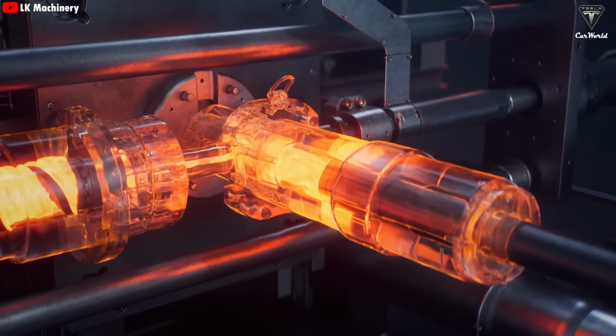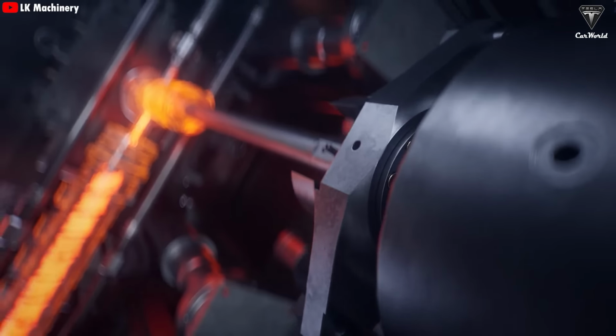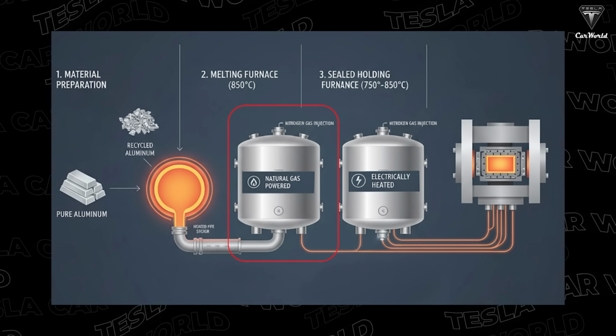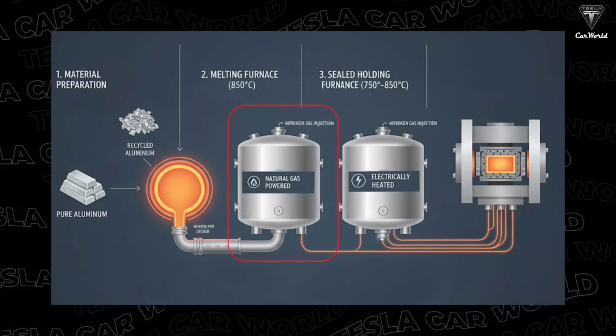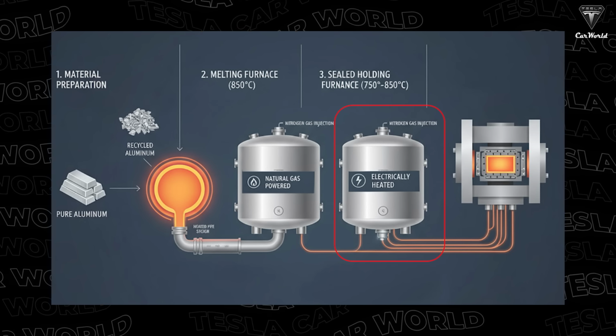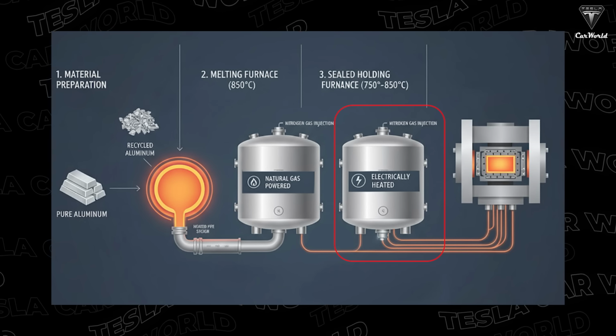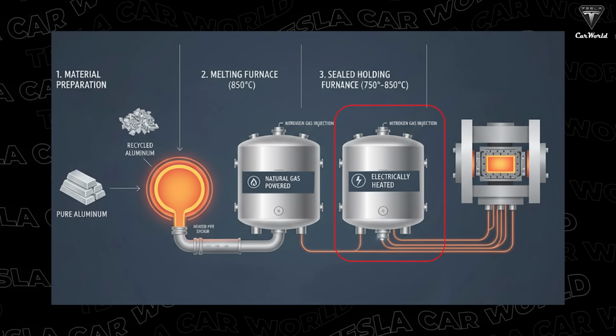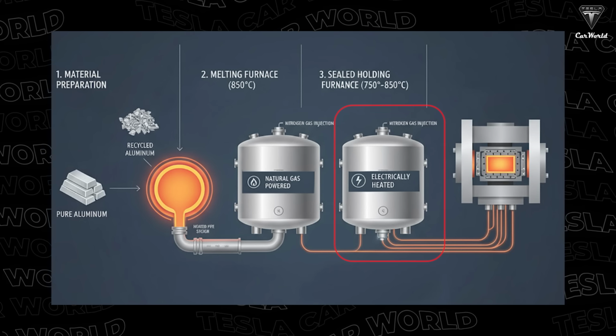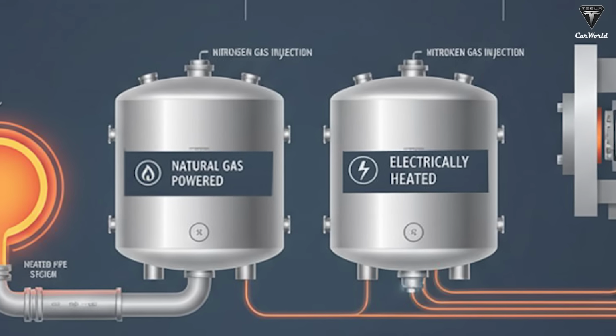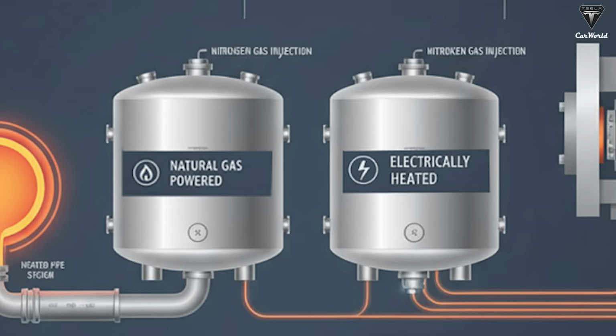The new Gigapress uses a 2-furnace system to process the aluminum alloy. One furnace acts as the melting furnace, powered by natural gas and operating at around 850 degrees Celsius. The other furnace holds the molten metal and is heated electrically, maintaining a temperature between 750 degrees Celsius and 850 degrees Celsius. Electricity helps keep the temperature stable and produces no smoke or steam, allowing the aluminum to remain denser and structurally stronger. But it doesn't stop there. The empty space inside the holding furnace is filled with nitrogen gas, which prevents oxide from forming in the molten aluminum and helps maintain a stable temperature.